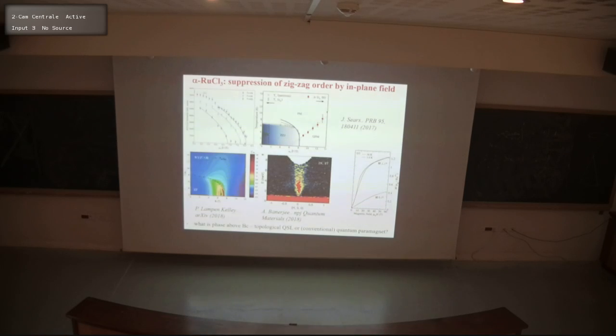And the question is, what is really happening in this phase immediately above, suppressing the long-range magnetic order? Whether really it's a topological quantum spin liquid or a more conventional quantum paramagnet. And there are certainly some very interesting measurements in inelastic neutron scattering which show that there's a very strong signal at the gamma point in the form of a continuum scattering.